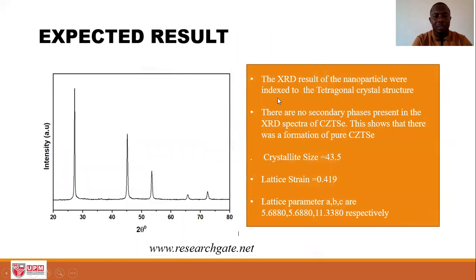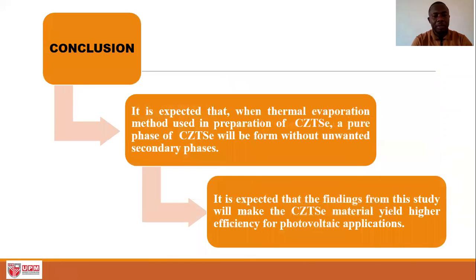Expected results. It is expected that at the end of this research, a pure sample or a pure formation of CZTSe will be formed, using XRD as the characterization machine. It's expected that the CZTSe pure formation will have no unwanted secondary phases. You can see the crystallite size of 43.5, lattice strain 0.49, 0.419, and lattice parameters a, b, c are respectively 5.6880, 5.6880, then 11.3380.